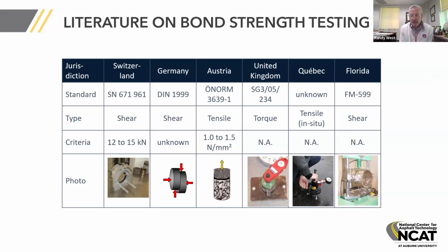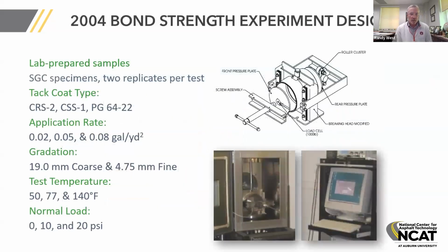And then I think the Florida method is very similar to the method we talk about later, the NCAT method, but it was developed probably about the same time that we were doing this study. So anyway, we ended up using a procedure much like is used in Germany, shown there, where they shear test with a normal load applied as a factor in the experiment. So it started out in phase one as a laboratory experiment.